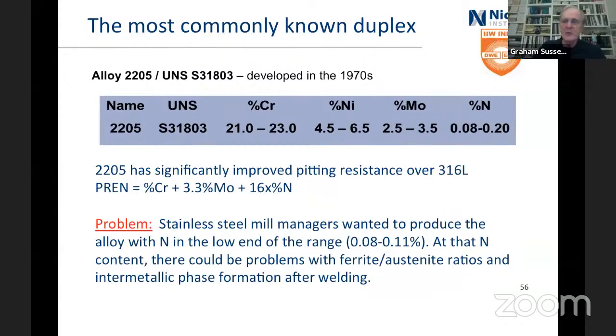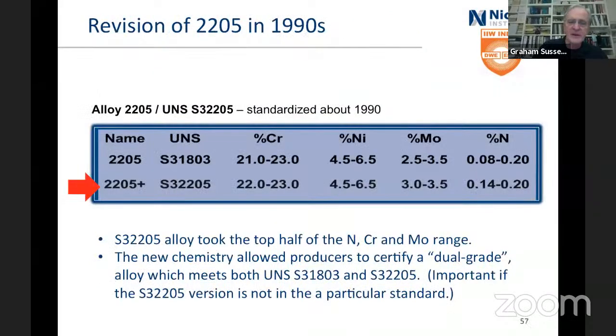The trouble was the stainless steel mill managers didn't want to put nitrogen in it. Goodness knows why, but they wanted to keep it down in the bottom end of the range. So where are we? Down here, 0.08 to 0.11 or 0.14, I think it was actually, was the limit. So they were going, yeah, in the right thing. But welding, you lose a bit of nitrogen, and so the ferrite-austenite ratios went funny and you got intermetallic phases. So about the 1990s, the people realized, and so they said, right, let's chop off the top half of these ranges, both the chrome, the moly, and the nitrogen, and we'll give that a new UNS designation, S32205, which is 2205 plus.